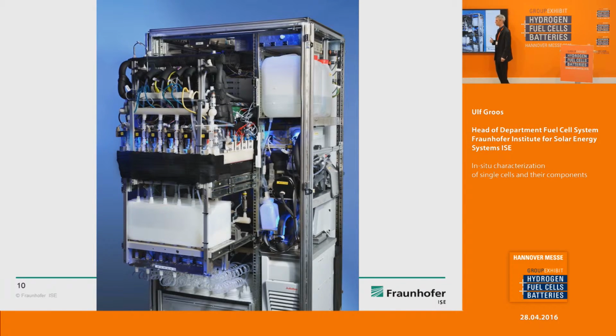So pressurized up to 1 bar, it's temperature controlled. We have humidifiers in front. And with this test bench, you have great possibilities to investigate many different materials at the same time, or one material under different operating conditions, like variation of the stoichiometry, variation of temperature, variation of humidification, variation of load profiles. And in one test bench, you get many, many results, which otherwise would make necessary a broad variety of single-cell test benches. So this is a test bench where you can test 30 single cells in parallel.